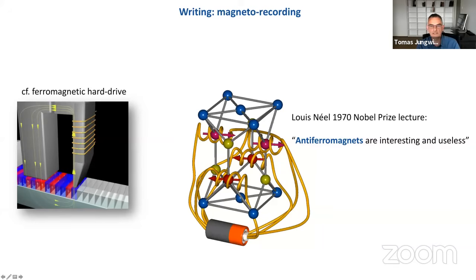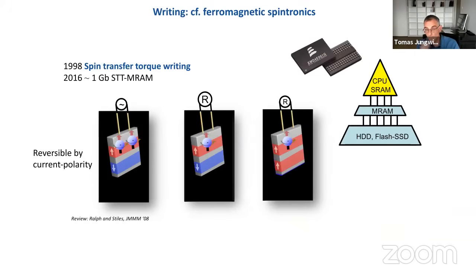So that seemed, and I think still seems, infeasible, but fortunately we live in the era of spintronics, where we have devices which use other means of recording or manipulating the moments than magnetic field, and that's spin currents. And so one of the phenomena that is used in commercial magnetic random access memories is the spin transfer torque, when from the reference magnet we inject spin angular momentum into the recording magnet and transfer the spin angular momentum, and this causes switching of the magnetization in the recording magnet. And the fantastic feature of this effect is that we can control the switching by just changing the polarity of the current.